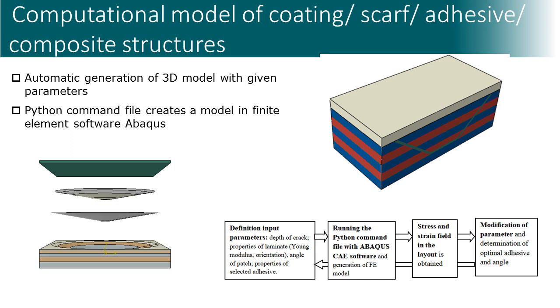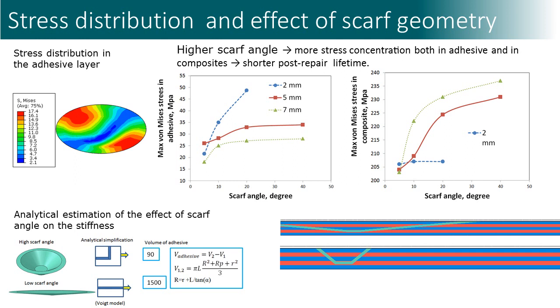To analyze the stress field in the repaired laminate, we developed a Python code, which automatically generates computational models of the repaired system. The model includes coating, scarf, adhesive, and laminate with several anisotropic layers. The parameters of the model, such as thickness of the layers and coatings, and properties, can be easily modified. The computational models allow the analysis of the effect of the scarf geometry, scarf angle, and adhesive thickness on the stress and deformation of the repaired structure.